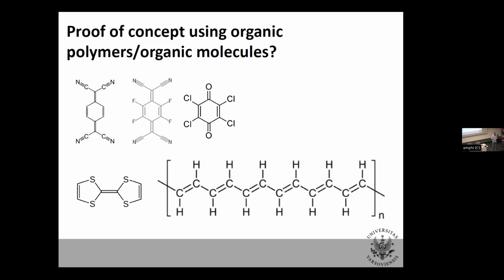The experiment I propose is, and I emphasize, very different. Place a layer of strong organic oxidizer on some substrate. Place a separator, and then place a layer of organic reducing agent, and monitor optical and electric properties, because they will change dramatically. From insulators, you will get metals, shiny, reflection, everything will be changed. So you could use polyacetylene, you could use TCNQ, maybe tetrafluoro TCNQ. One aspect here is that if instead of using polymers with a band structure, you use molecules, you will have charge transfer, of course, but you will not have metallicity due to polaron formation. But this is another story.